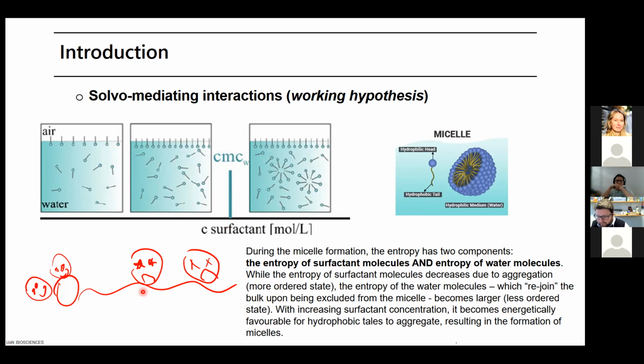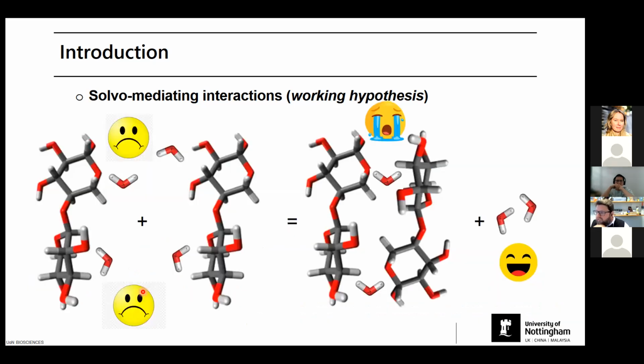So we have this hypothesis about how these polysaccharides interact, taking this information from the DSC data and the relaxometry data using the proton relaxation. We have the hypothesis that obviously the water is associated with this polysaccharide due to the enthalpic gains, but entropically it is very unhappy. And when you have association in this case, you still have retention of water.